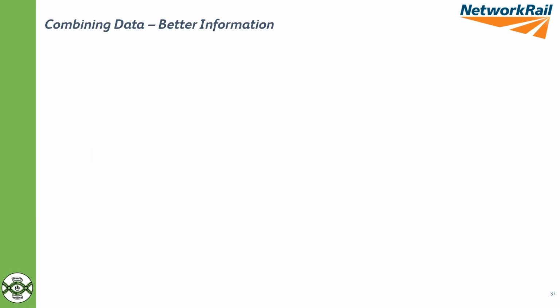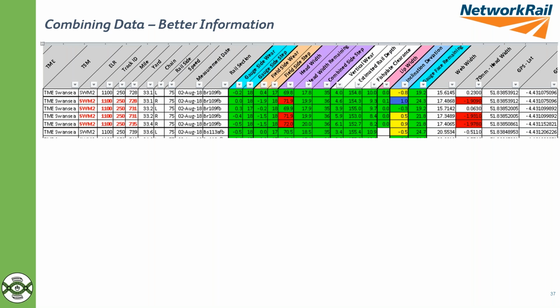On the subject of linking the data together, it's something I've been pushing to do. We can go looking for new data, but often it's data we already have. This is an example. This is our rail profile information that's currently measured by laser systems on our UTUs. I won't go through it all in detail, but the bits I've highlighted in red are effectively a measurement of the width of the head. And you can see at that location, we've got something that's 71.9, 72 wide, compared with the rail around it at 69.8. So it's not a heavily side-worn bit of rail, fairly reasonable condition, a bit of vertical wear, 4 or 5 millimeters of vertical wear, but this localized widening.